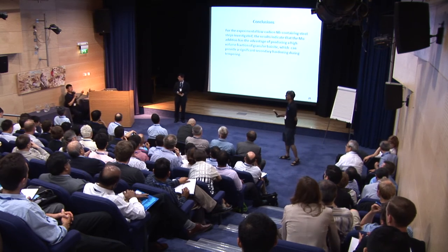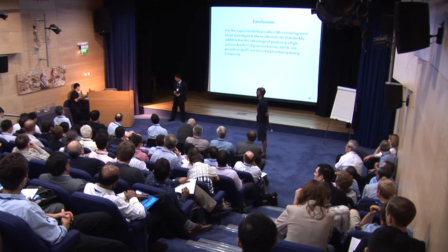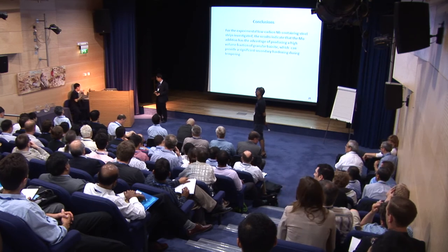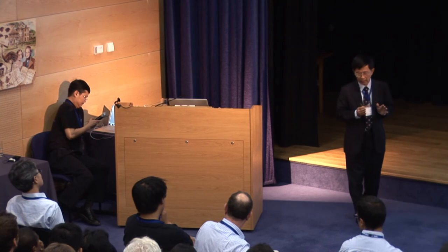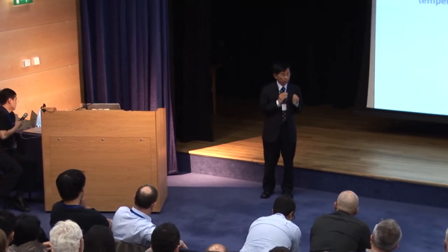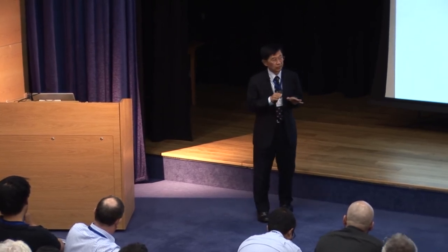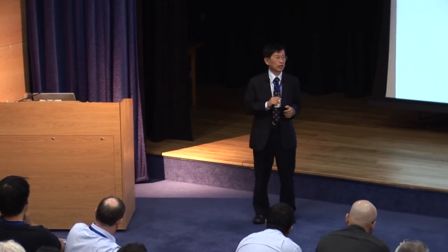We have a question from online. David Hodick asked, in the experimental procedure you refer to AC, air cooling. Is that air cooling from a 5 mm thick strip or a commercial simulation? After isothermal transformation at, let's say, 450 degrees C, the strip cools naturally to room temperature. We suppose the bainite is already there, so we don't need to use fast cooling at the final stage.